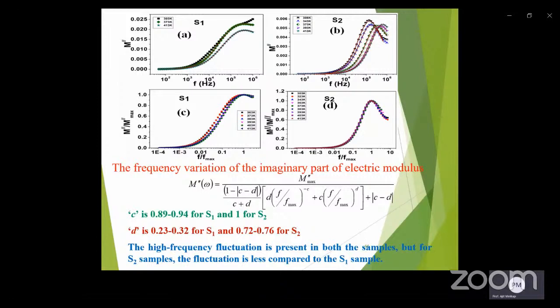The normalized electric modulus for S1 and S2 sample are demonstrated here. The normalized curve for S1 sample does not match on a single master curve, although for S2 sample they overlap on a single curve. So for S1, the dynamical properties change with temperature, whereas for S2 sample, it is temperature independent.